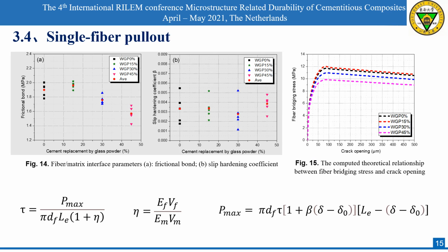Figure 14 presents the frictional bond stress and slip hardening coefficient between the fiber and the matrix. When WGP content is 15%, the maximum frictional bond stress was 1.96 MPa. The large frictional bond strength represents the large load required in the tensile process. It can be seen from Figure 15 that the maximum fiber bridging stress occurred in the specimen with WGP 15%, and then tends to decrease when the WGP content exceeds 15%.